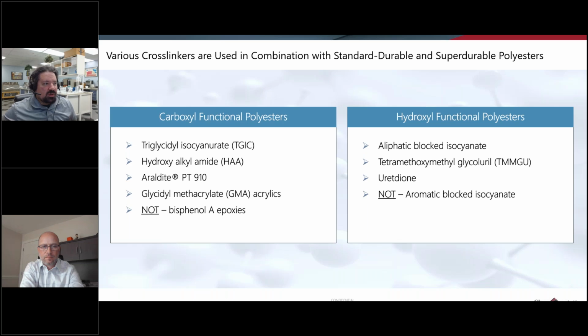Crosslinkers. I probably don't have to get too far into this, but for the carboxyl functional or acid functional polyesters in North America, we still use TGIC. It's pretty great, but there are regulatory issues. In Europe, they completely shy away from the use of TGIC. Instead, there's HAA or Primid that they use as a curing agent. You can actually use acrylics to cure with a polyester. That is a useful way to adjust the gloss, because the incompatibility of them makes it a pretty nice lever to pull for a gloss adjustment.